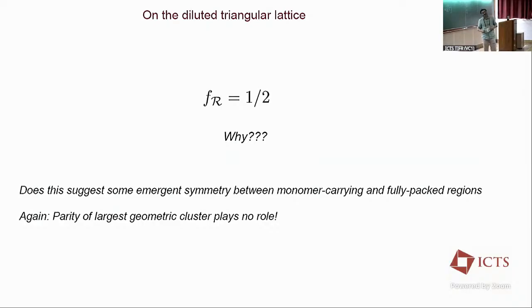Here, there's nothing like that, but it's behaving like that, right? So I don't know why. I have no idea. But it has a consequence, and the claim is the heat conductance coming from these Majorana modes will be absent if the sample is p-type, present if it's r-type. So at the very least, you're going to get some very dramatic violations of self-averaging. So if I make a histogram of heat conductance in such thing, because there is a contribution that's missing in half the samples, I should just get two well-defined peaks, not even a single broad distribution, just two peaks. So it's in this sense that I'm saying half the samples are in one phase and the other half are in another phase. Right? That's the claim.